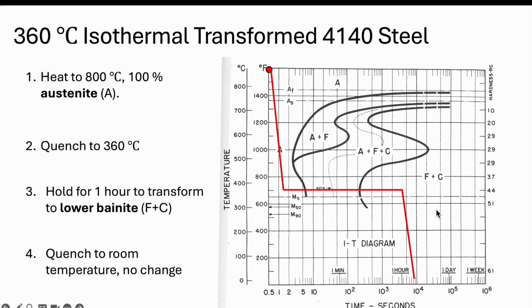And the key here is that you might notice that it crosses the martensite start, 50% and 90%. So you might say, okay, now it transforms to martensite. That is not the case. You have to remember that all of these reactions, whether it's ferrite, cementite, or martensite, start with the austenite phase, this one. So if we already have the equilibrium ferrite plus cementite, it's not going to transform into martensite. So once we're already on this side of these dark lines, that material is not going to transform to martensite. So we would just have lower bainite, and there's no change when we go from 360 to room temperature, at least from a phase perspective. There's no change in phase.